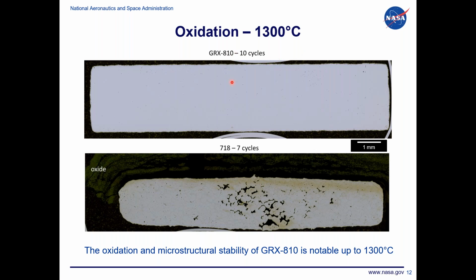This is GRX-810 on the top here after 10 cycles at 1300 C. You can see there's a thin oxide layer that is formed, but otherwise the microstructure is very stable. We don't see gross porosity forming or anything like that. Whereas with 718, you have this huge oxide layer that is formed, and clearly the microstructure has started to fall apart, either through incipient melting or some other mechanism, maybe just massive diffusion to form the oxide layer. And so clearly at these conditions, 718 would have no structural properties of use, whereas GRX-810 would still be usable.